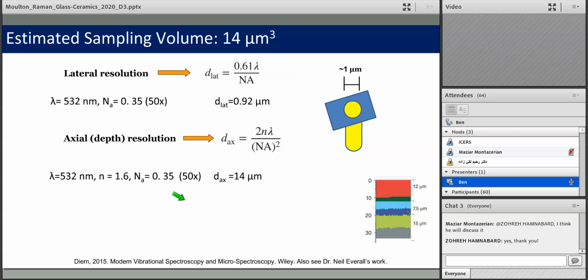Another very important variable is the actual volume of the scattered light you're looking at. And you'll see in many, many papers report a lateral resolution of a micron. That lateral resolution is determined by this relationship here, where 0.6 times the wavelength of the incident radiation divided by the numerical aperture of your objective. So just for argument's sake, I've put our green laser 532 with a 50 times long working distance objective that has a numerical aperture of 0.35. And you can see, indeed, the lateral resolution is about a micron. And I've actually hit waveguides that are a few microns thick and seen that, indeed, this is true. You can get a lateral resolution of a micron.